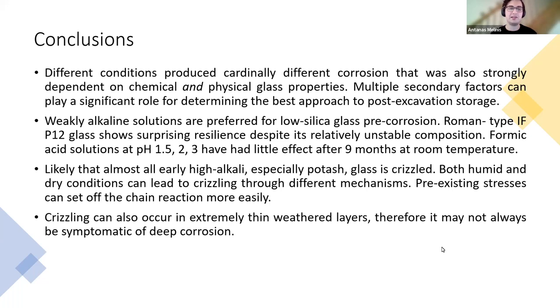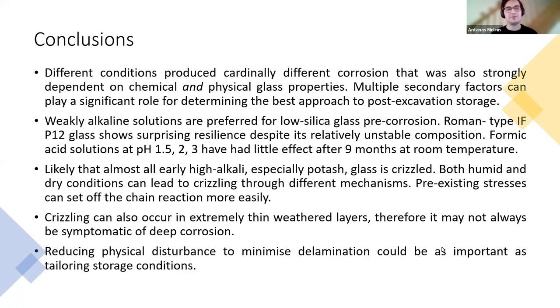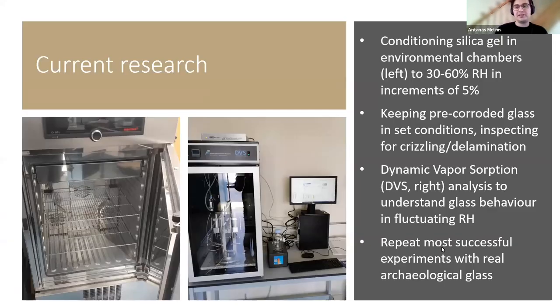It can also occur in extremely thin layers, so may not always be symptomatic of deep corrosion, which could be encouraging to conservators, meaning that the crisling and flaking may not always result in this considerable loss of the scientific and artistic value of the piece. And we should reduce physical disturbance to minimize delamination, because it could be as important as tailoring storage conditions. So currently, my plans are to pre-corrode the glass, leave it in set conditions between 30 and 60% RH in steps of 5%, and track their weight, track their delamination to see which conditions would be optimally responding to these pieces.